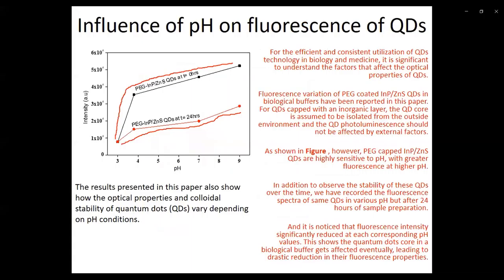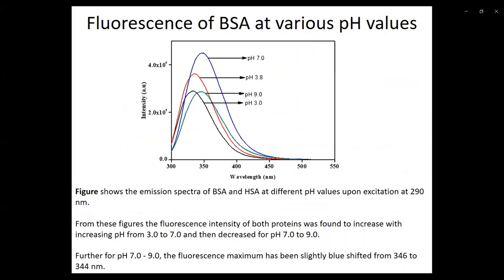Quantum dots have maximum fluorescence intensity in the basic region, that is at pH 9, and less fluorescence intensity at pH 3. And after 24 hours, there is a drastic reduction in the fluorescence intensities of quantum dots, which shows the instability of the quantum dots. This shows the fluorescence spectra of BSA protein at various pH values.